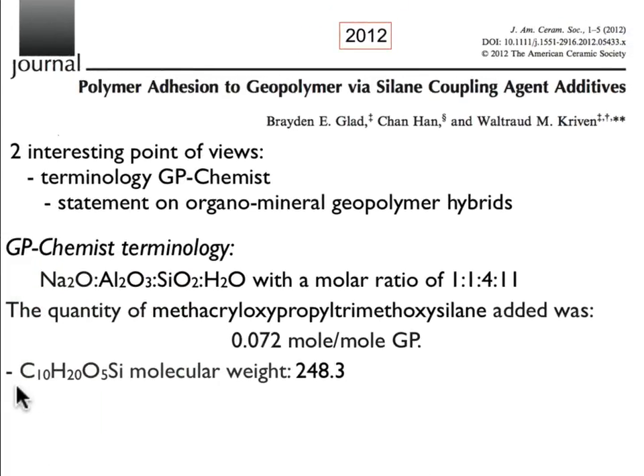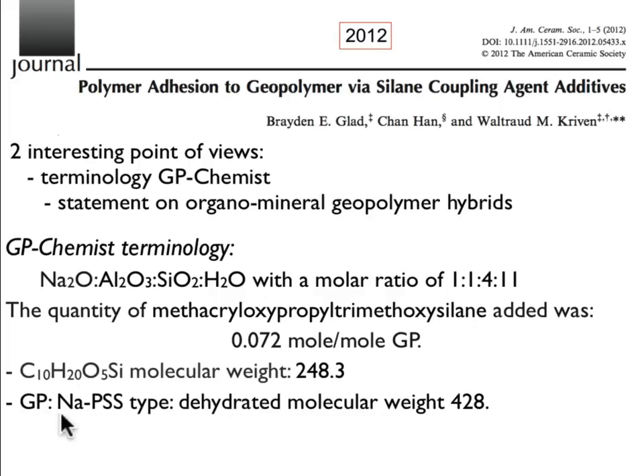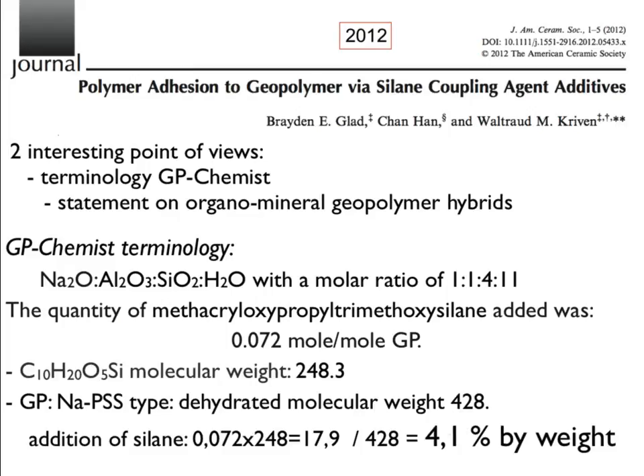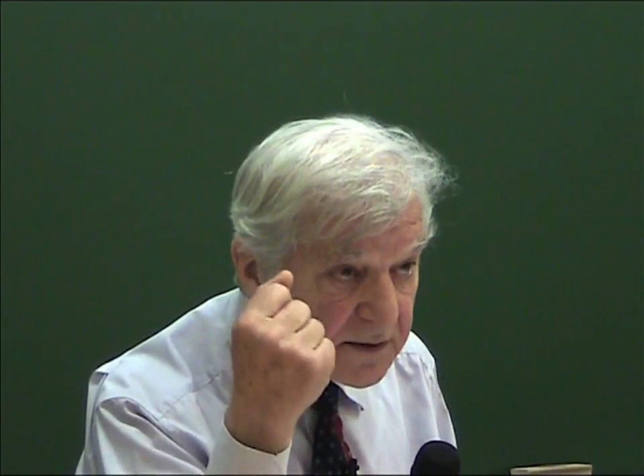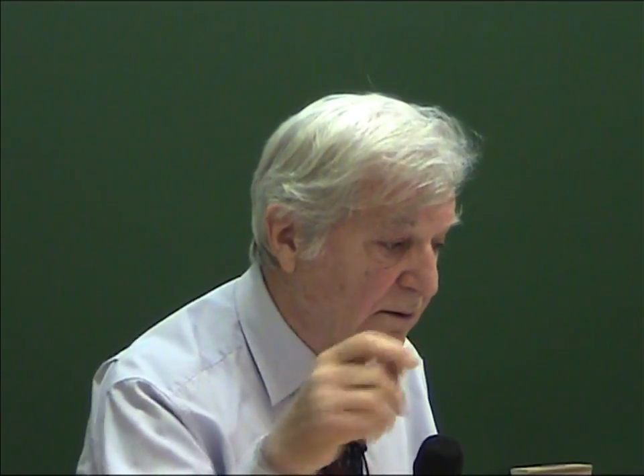So, small calculations. The molecular weight for the silane here is 248. The molecular weight of the geopolymer, this is an Na-PSS type, here I took the dehydrated form, has a molecular weight of 428. So we know that 0.072 mole per mole of geopolymer means 4.1% by weight. But this is a type of reasoning that is important. This is a way of using the terminology and understanding it and propagating it.